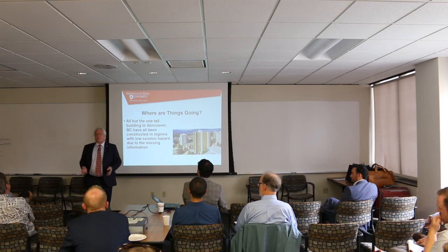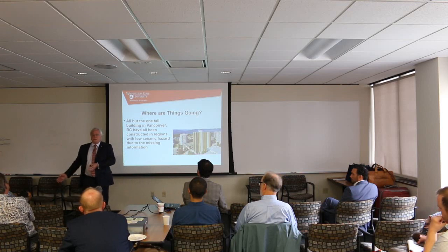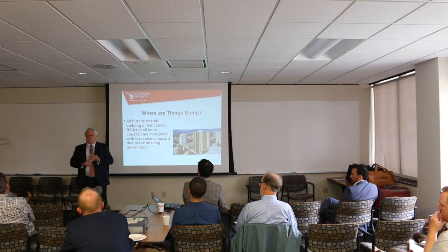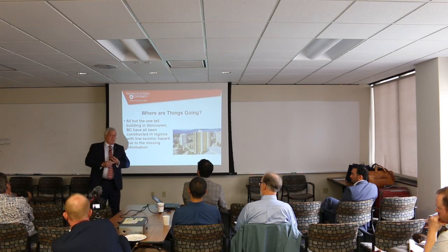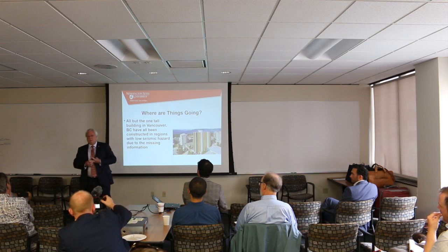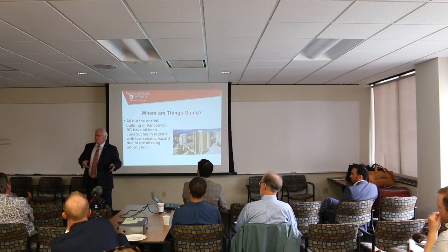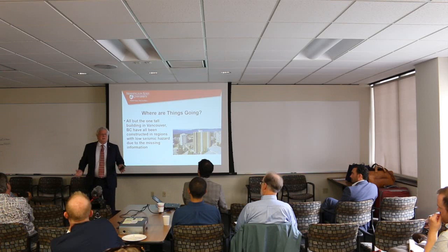That's the material. Every material you design with, I don't care if it's concrete, steel, they all have an Achilles heel. They all have a weakness, and we design these materials for their strengths and to avoid their weaknesses. Concrete can't take tension, so we put rebar in there. Wood can't take tension perpendicular to the grain, really bad, so we don't load it that way. Cold-formed steel can't take compression very well either, because it buckles too easily in local buckling. Every material has its weaknesses and strengths. We have to design them for their strengths, avoid their weaknesses, and combine them to make the buildings we want to see.